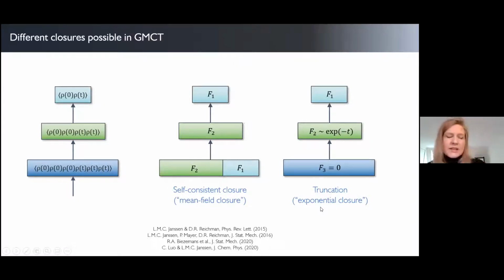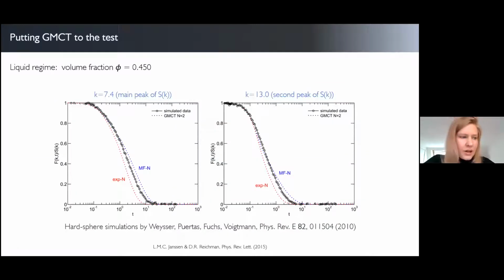And it turns out, and that's entirely non-trivial mathematically, that these two families of closures actually give us an upper and a lower bound for the predicted dynamics. And as we apply these closure approximations at higher and higher order, they will systematically get closer and closer to each other and gradually approach the infinite order solution. But that's both mathematically and physically, I think, non-trivial, that this convergent behavior is in this framework. All right, now with that, I'd like to show you some results.